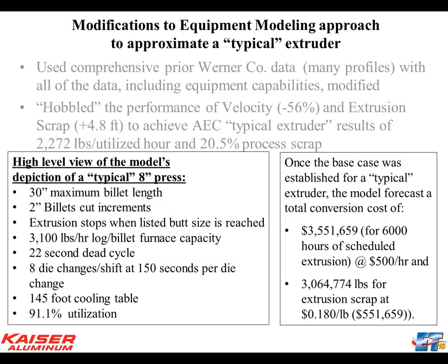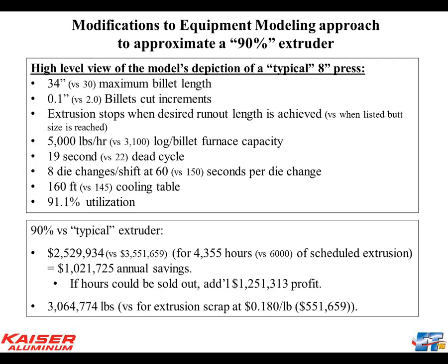That was for 6,000 hours of scheduled extrusion, basically, 5 days a week, 250 days a year. And out of that, we would generate just over 3 million pounds of scrap. I had a scrap valuation of about 18 cents per pound to send it out, get it processed, and get it back as log. And that was $3.5 million to do it on a typical press.